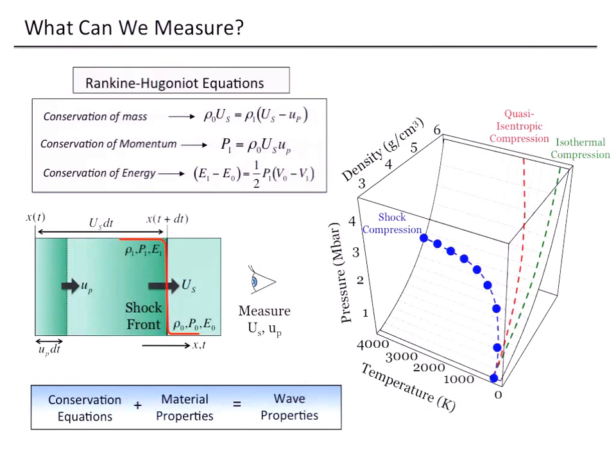Those of you that do shock experiments will know the Rankine-Hugoniot equations. These are just conservation equations - conservation of mass, momentum, and energy. And so typically what we measure are velocities. If you have a shock front propagating through a material, you have the shock velocity and also a particle velocity, which is the actual mass velocity behind. What the Rankine-Hugoniot equations do is relate the properties, the initial state of the material in front of the shock, to the shocked properties, or the compressed density, pressure, and internal energy.